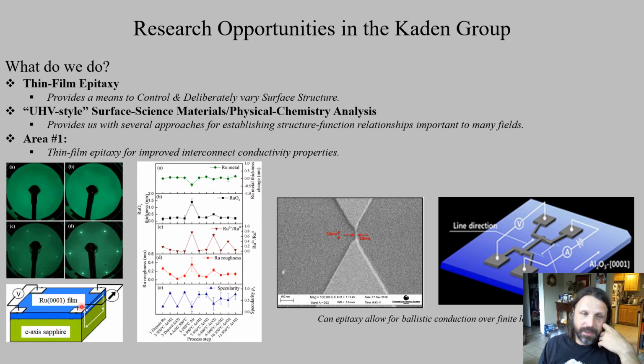What that means is we could turn the surface from fully specular, meaning very reflective like a mirror, to a fully diffuse surface. When it's fully diffuse, the resistivity goes very high because you're losing electron flow due to the scattering of electrons. When it's fully specular, the electrons keep their forward momentum, so you get minimal impact to resistivity. The reason we're interested in this is that power consumption in CMOS technology is basically at the interconnects. And copper is rapidly becoming obsolete because we've reached length scales where this surface loss becomes very important.